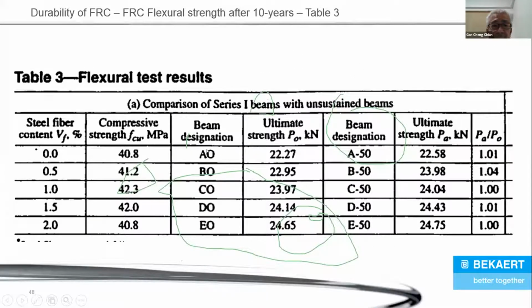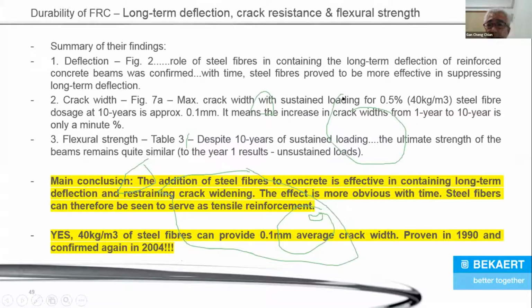And last of all is flexural beam test results. So they were comparing the flexural behavior of the beam in 1994 and the flexural behavior of the beam after 10 years. So here, 22.27, these are in year 0. Here, 22.58 is after 10 years. So in fact, after 10 years, it doesn't change at all. It doesn't reduce and it doesn't increase. It's still roughly the same. That's why PA over PO is equal to almost 1. So these are the summary of their findings.